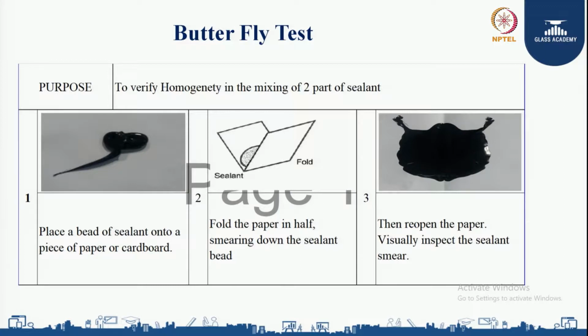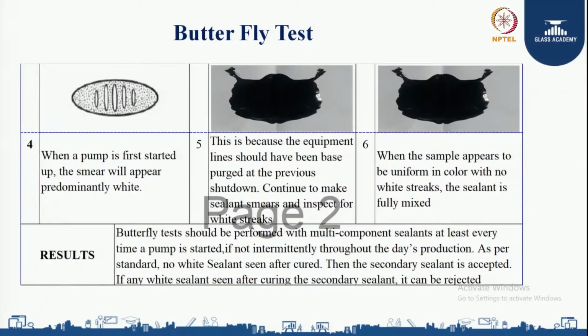Place a bead of sealant onto a piece of paper or cardboard, then fold the paper in half, smearing down the sealant bead, reopen the paper and visually inspect the sealant smear. When a pump is first started up, the smear will appear predominantly white, because the equipment lines should have been base purged at the previous shutdown. Continue to make sealant smears and inspect for white streaks. When the sample appears uniform in color with no white streaks, the sealant is fully mixed.